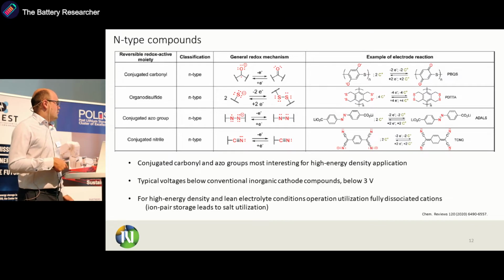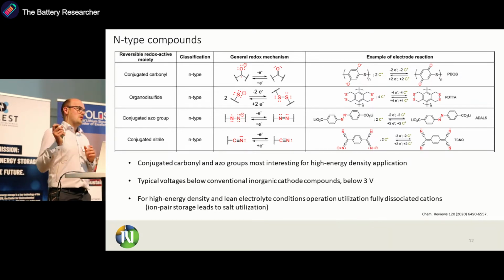And like I said before, for having high energy density and operation in lean electrolyte condition, we need to really utilize fully dissociated cations. So it means that we should not have ion pair storage. We should put in just calcium 2+, magnesium 2+, or aluminum 3+.